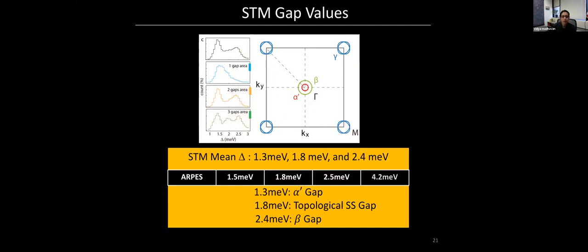The reason this is important is because then you can compare to ARPES and you can assign that this particular low energy gap at 1.3 meV is the alpha pocket. This is the topological surface state, and this is the beta pocket.